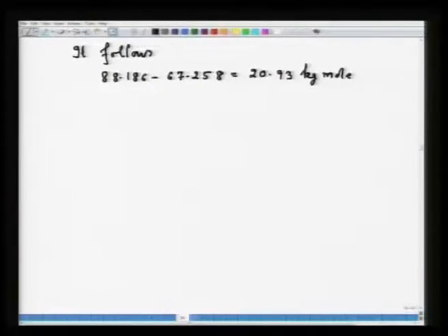So, this difference between the gas that you determined from zinc balance and the gas which you determined from the CO2 CO exit ratio and the appropriate kg moles of ZnO and PbO, there is only the possibility that 20.93 kg mole is excess air.